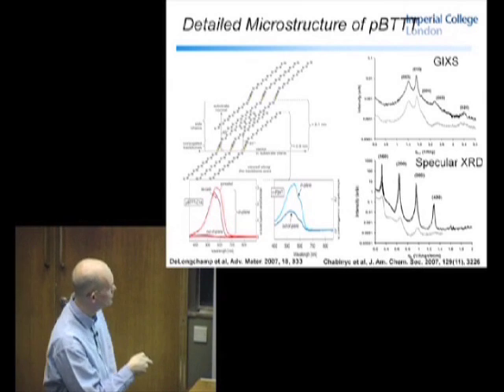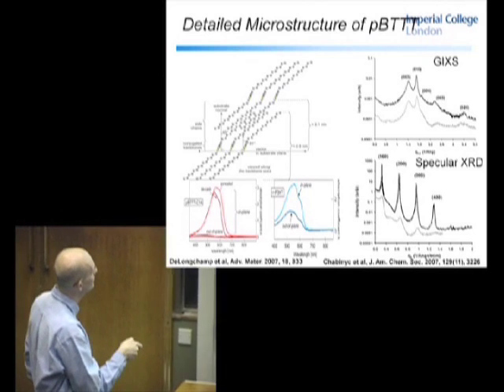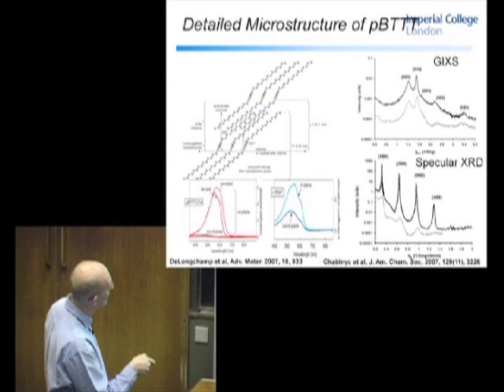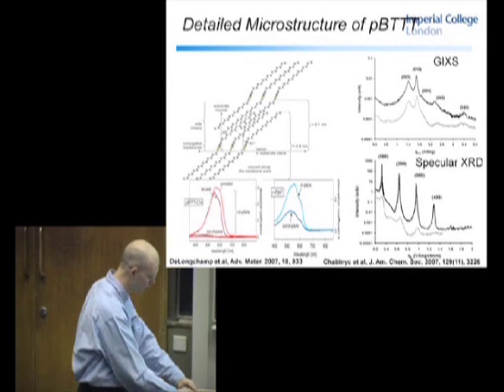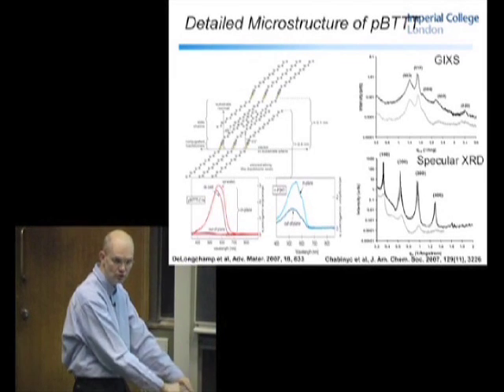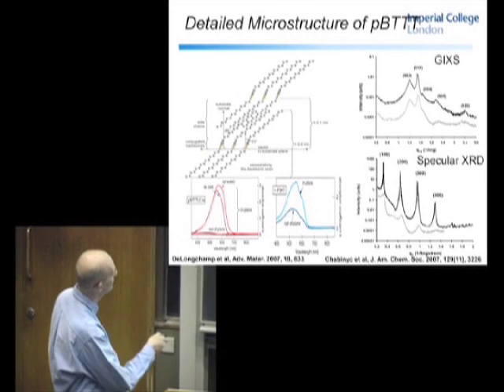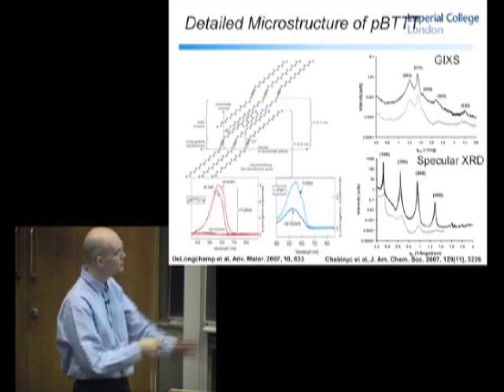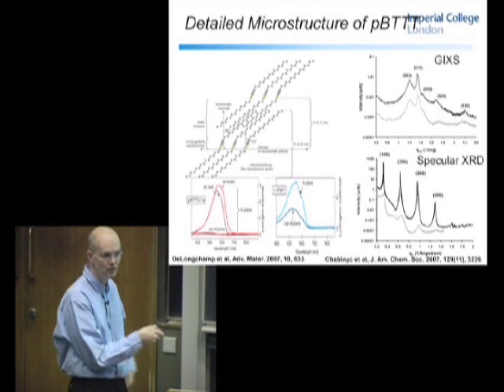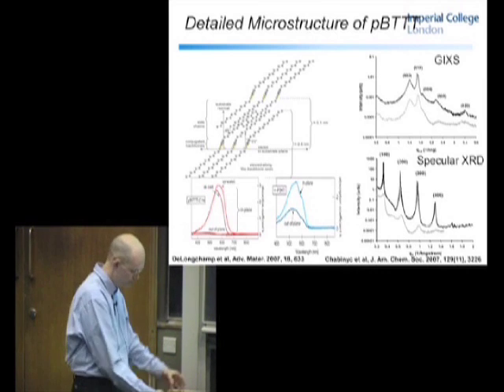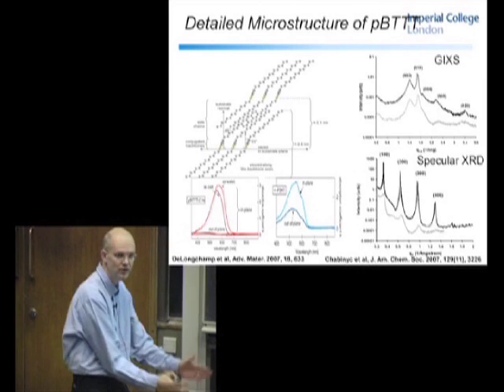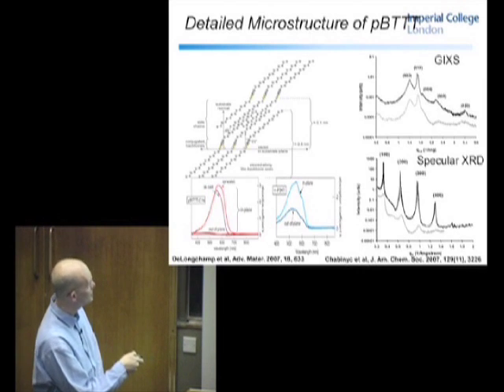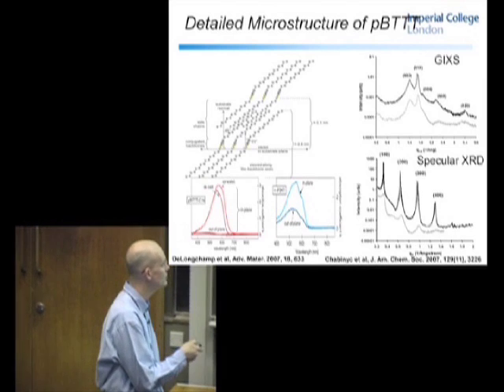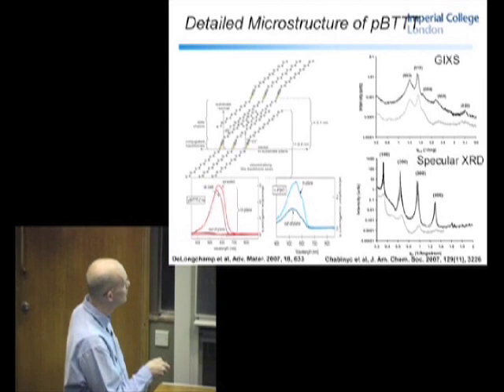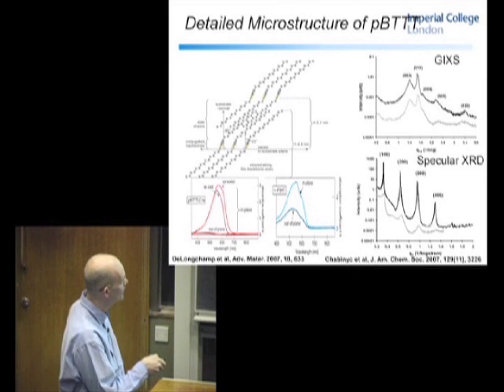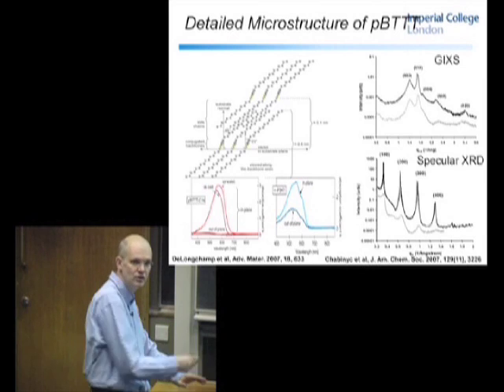And you can also see this from spectral ellipsometry. So again, you're probing here the absorption coefficient in the plane. So if you imagine the long rod, the optical axis is in the plane, so the absorption is pretty high in the plane. Whereas if you look at the out of plane absorption, there's absolutely no absorption at all. So you see that these conjugated backbones are more or less completely in the plane of the molecule, whereas P3HT, this is regioirregular P3HT, which up to a couple of years ago was the benchmark organic semiconductor, you see a significant out of plane absorption, so you get this misorientation that's occurring.